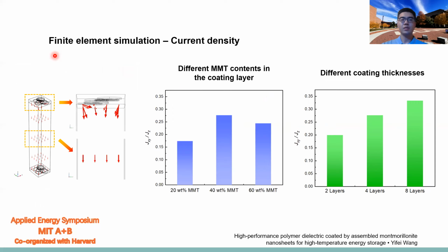So we did some finite element simulations to try to find the reason why these coated polymers can have enhanced energy storage performance. The first thing we simulate is the current density inside these coated polymers. Because the MMT has anisotropic conductivity and a relatively higher surface conductivity, we can find that the current is regulated from the Z direction to the in-plane direction. So it means that these MMT coatings can regulate the injected charges, dissipating them along the in-plane direction.